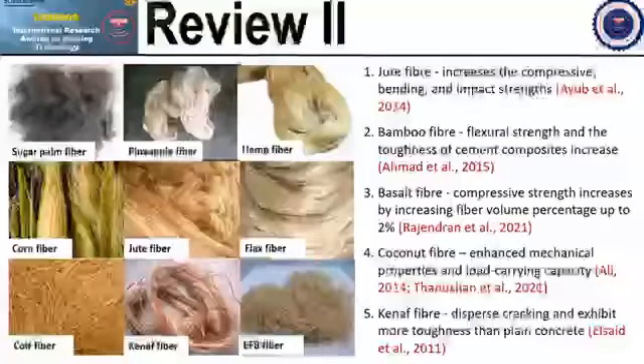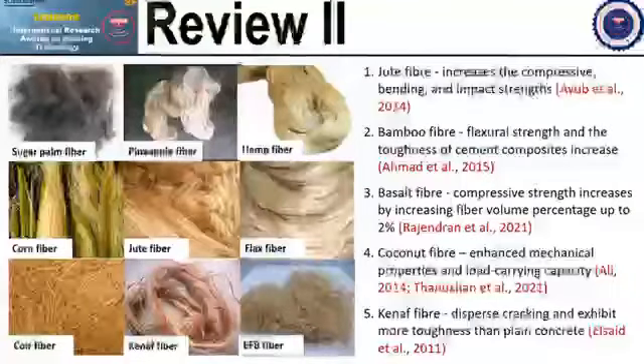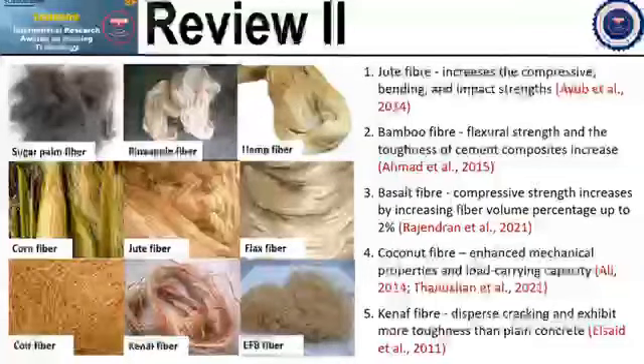Okay, several researchers reported findings on the reinforcement of jute fibers in concrete in order to increase the compressive strength, flexural strength, and impact strength. The result revealed that the properties improved through the reinforcement of the jute fibers up to a certain limit.